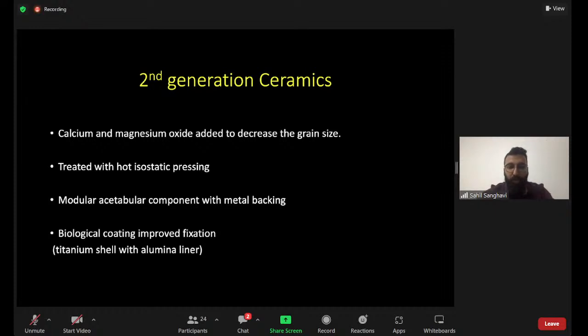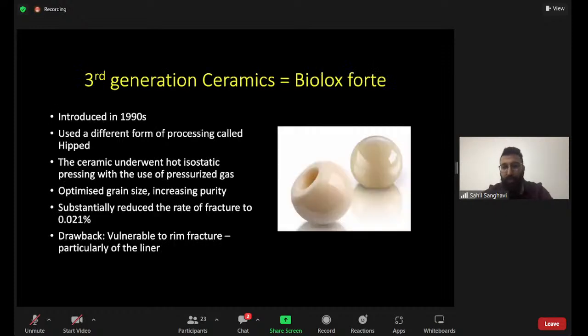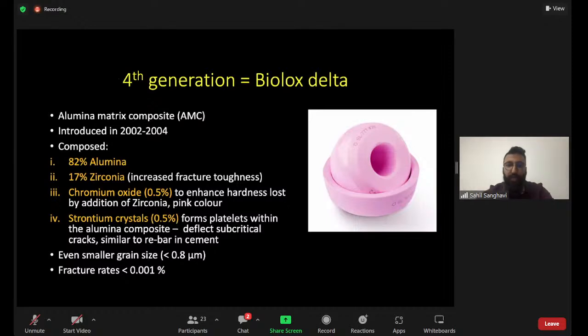That is, the biological coating improved fixation. So most of these were titanium shells with alumina liners. However, fractures were still a concern with other drawbacks of ceramics, which led to the third generation ceramics, or Biolox Forte, that was introduced in 1990s. And this used a different process of manufacturing, but the main advantage here was it optimized the grain size and increased purity. However, the head fracture rates did go down, but it was still vulnerable to the rim fracture of the liner. So this led to the fourth generation of ceramics, which are in use today, and that is called